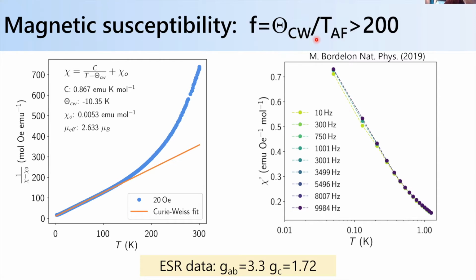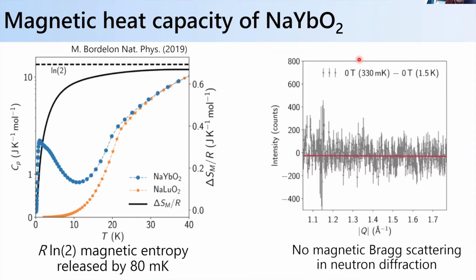So basically an upper bound on when it could possibly order, which is 50 millikelvin, so that gives you about a 200 Kelvin frustration index, which is really starting to imply that you're in a regime of intrinsic quantum disorder in this material. And so we can look at it a bit more. Here I've shown you the heat capacity of the same sodium ytterbium O2 system as a function of temperature.